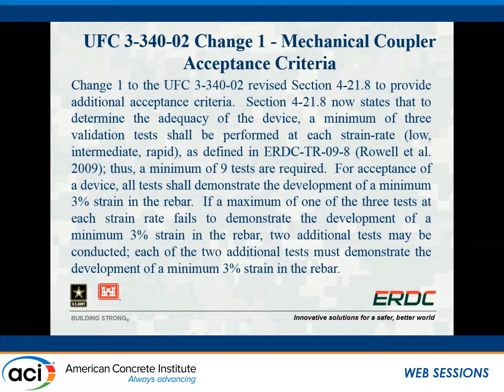So it defines the way the test is conducted, the strain rates that have to be considered, and those are referenced back to that ERDC-TR-09-8 with a minimum of 9 tests, so you do triplicate tests at your 3 different strain rates. And so the acceptance limits for this, now we have an actual quantitative ductility limit rather than just saying it has to match the properties of the bar itself. We can reduce that and allow for some reductions in ductility based on the coupler.